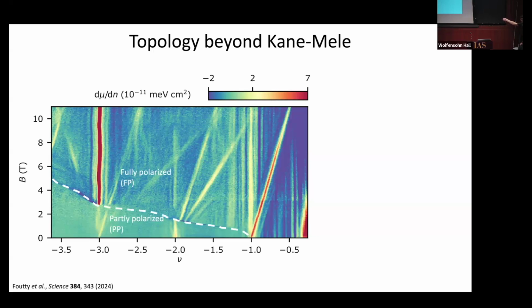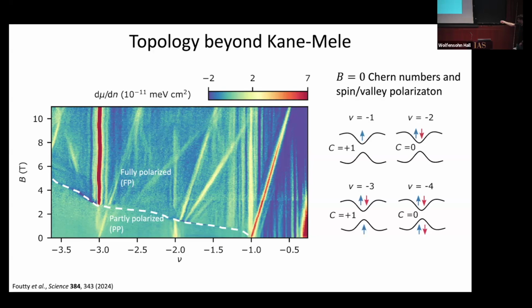This is presumably fully spin polarized, similar to the transition that I was showing you in the heterobilayer data, whereas down here we expect that we're partially spin polarized. That is, the first state occupies one of the spin valleys and gives quantum anomalous Hall physics. Presumably at nu equals -2, we have this scenario where you have both of the first Moiré bands occupied, but their topology cancels out. This transition here is the transition between partial spin polarization and occupying just these two blue arrows alone. At nu equals -3, we have, again, this topological state with one of the spin valleys occupied.